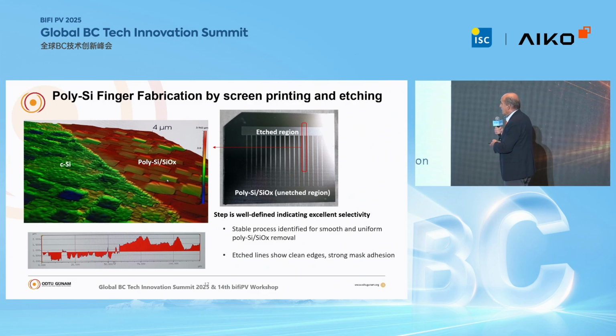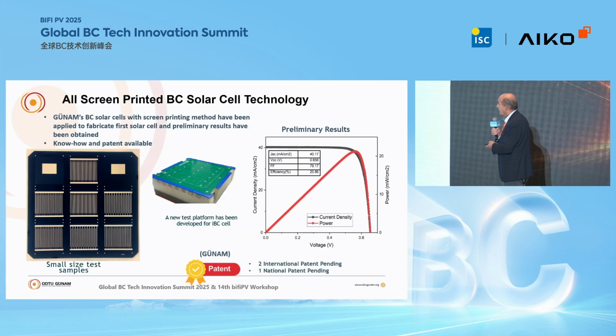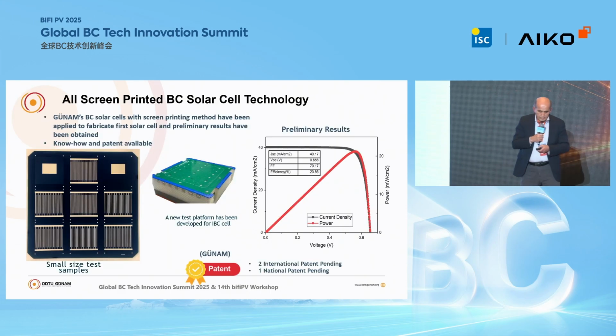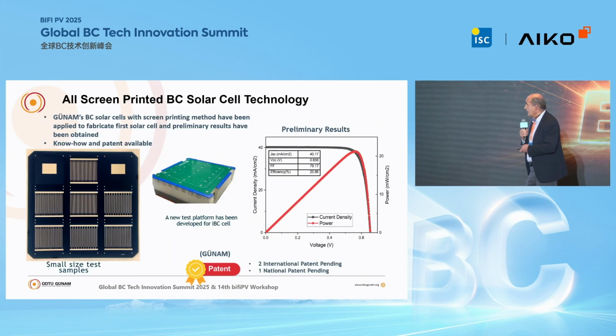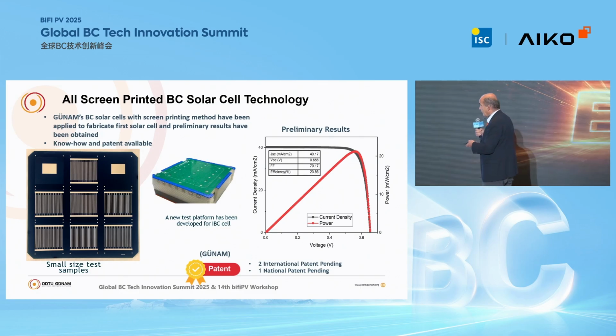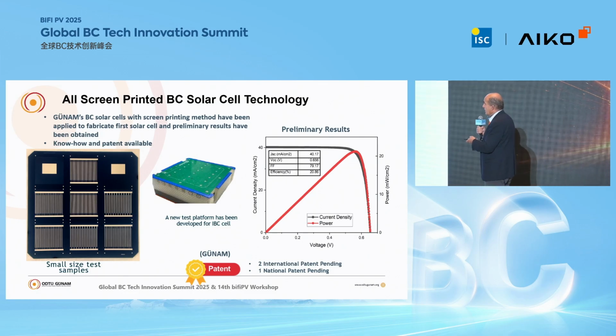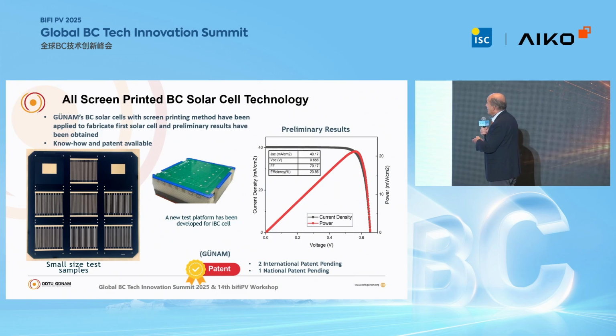So there is no undercutting. The mask is working quite well, so it is a promising technique. And we actually apply this screen printing technique to fabricate small test samples with these sizes, as you see. And these are the first preliminary results, and it's quite promising.